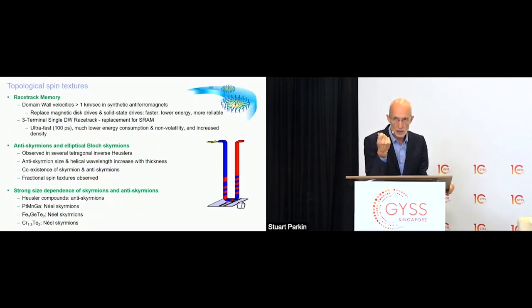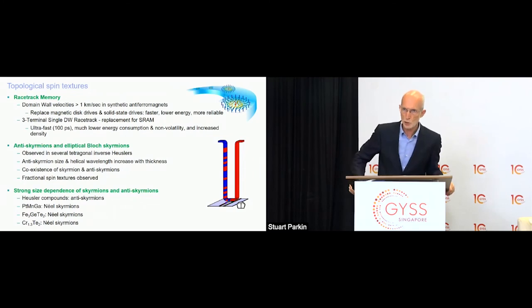And if we've already demonstrated we can make racetracks that are just 50 nanometers wide with the same high efficiency of motion of the domain walls, this means we could build racetrack devices that could replace magnetic disk drives with super high capacities. And at the same time, if we build a racetrack which is super short with a single